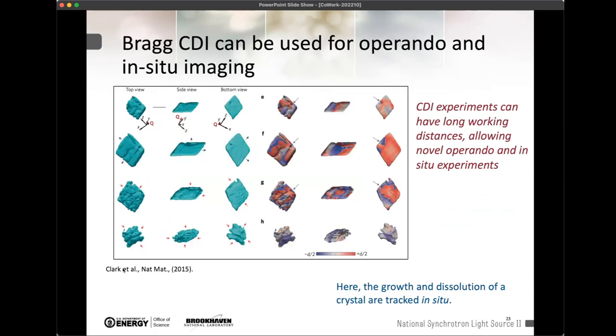Jesse Clark at Argonne, at Ross's beamline 34-ID-C, looked at a calcite crystal and monitored its growth and dissolution in situ. These experiments typify what we were thinking about when we developed the capabilities for the CDI beamline: we want to look at deformation, defects, and monitor things in time. That has carry-on effects on the beamline design — you have to provide a great deal of space in the vicinity of the sample to allow the beam to be properly conditioned and allow sample setup. You also have to maximize the flux on the sample to push the time resolution as far as is reasonable.